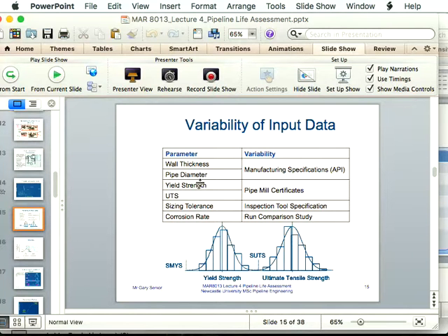So just, in the future, if you come across an X-whatever graded pipe, don't assume that all the material in that pipeline meets that grade, because it won't, because they've got distributions associated with them. Generally, as a rule of thumb, the average mean yield strength of line pipe steels is normally around 10% above SMYS. Okay, so if you've got your certified X65 450, in reality, if you looked at all the material test certs and plotted it all up, you'd come up with near a 480, 490 newtons per millimeter squared.